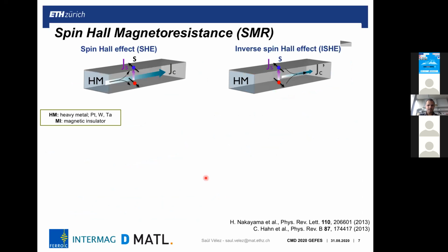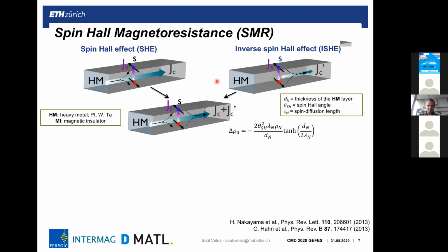So in the first part, when we have a spin Hall effect and an inverse spin Hall effect in heavy metal layers, if you put both effects together, you have an additional charge current generated because of the combination of the charge-to-spin and spin-to-charge conversion. This additional current leads to a reduction of the resistance of the material, but this amount depends on the spin transport properties of the material as well as on the thickness of the heavy metal layer.